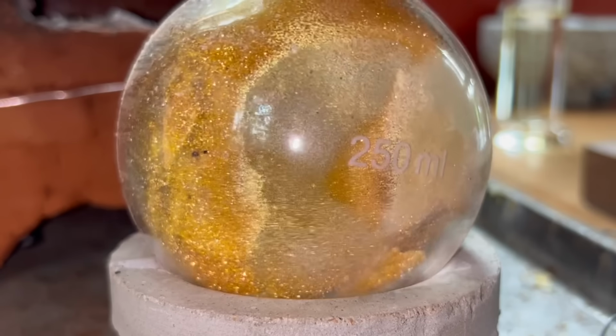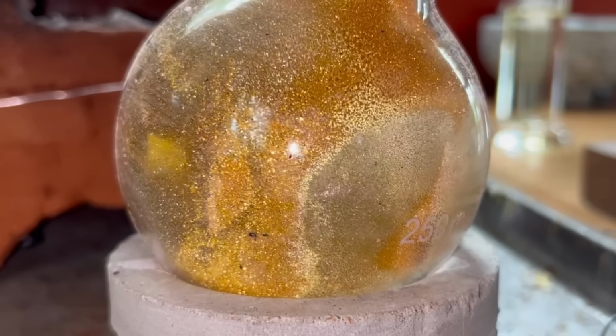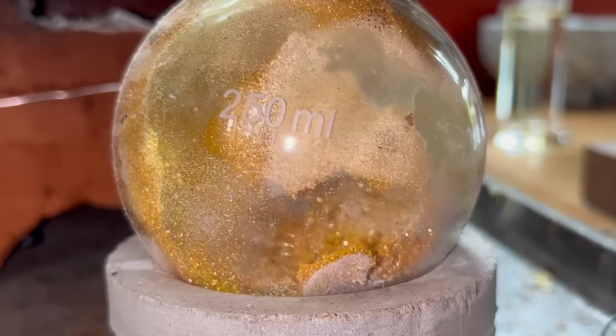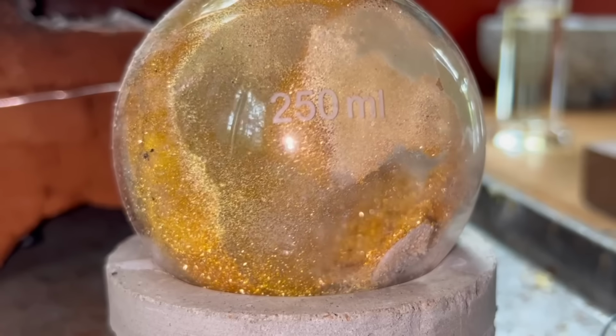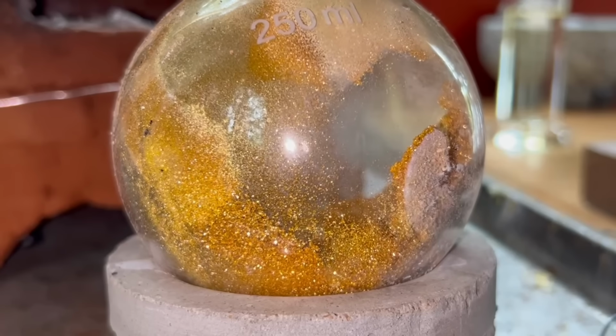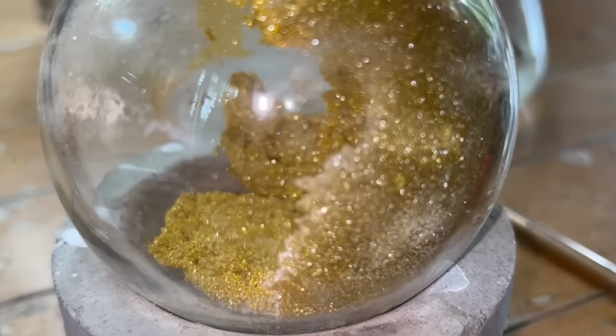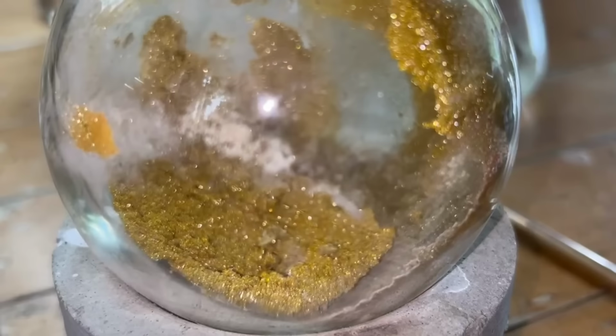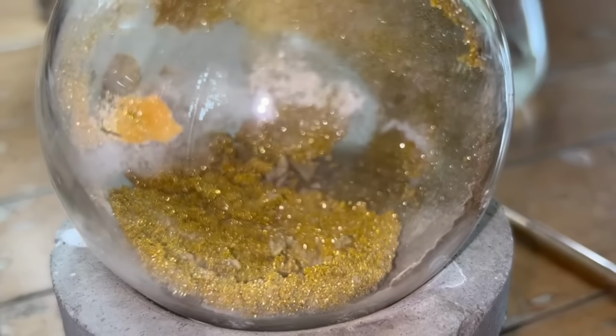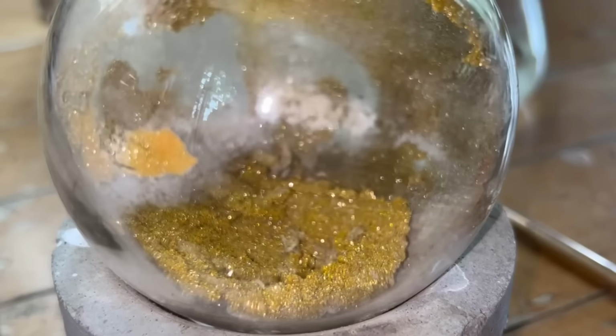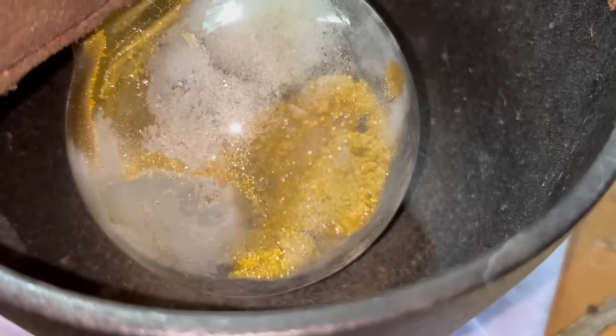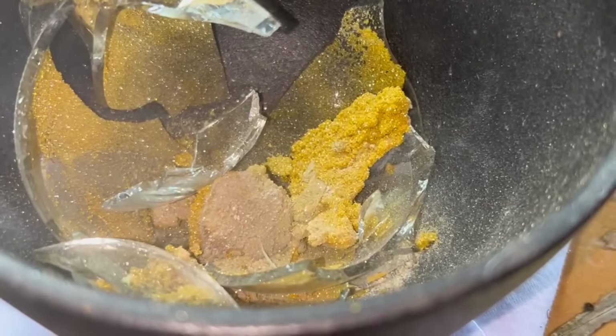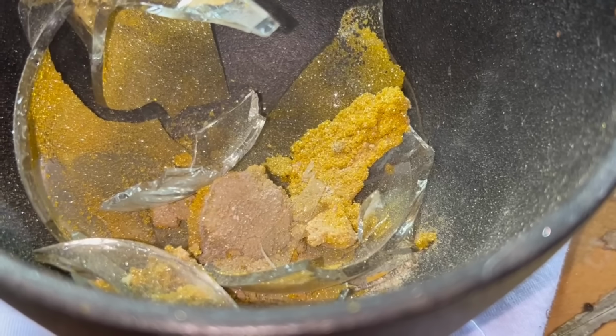Though they had appeared a copper red in the heat, as they come down to room temperature, the metallic flakes become increasingly, even brilliantly, golden, telling me the reaction worked exactly as it was meant to. To get a closer look, the flask is smashed, revealing that the whole of the tin has been converted into this golden powder.